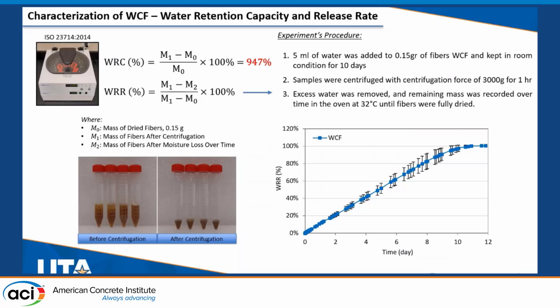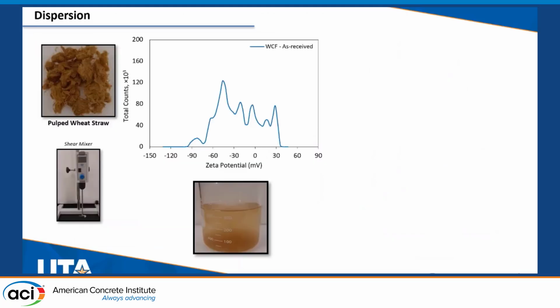For determining water retention capacity, I used the standard centrifugation technique such that a certain amount of fibers is soaked in water, left to be fully saturated, and then their mass after centrifugation was periodically recorded while being oven dried. And based on our measurements, these fibers could successfully absorb nearly 10 times their weight and release it in approximately 11 days.